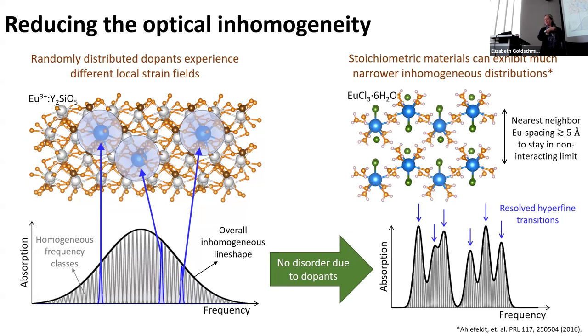If I grow a stoichiometric crystal where I don't have any doping, my rare earth atom lives in every site that it should live in, and I get rid of at least that source of inhomogeneity. This principle has been shown: you can reduce the optical inhomogeneity by going to a stoichiometric material, though it's only been shown in materials that aren't really well suited to a lot of things. Also, you have to keep the atoms apart by more than you normally would in a normal crystal, so that they don't interact if they get too close together. For instance, yttrium orthosilicate, a very common host for rare earth atoms: if I were to grow Eu2SiO5 instead of europium-doped Y2SiO5, the europiums would be too close together. They would no longer act.